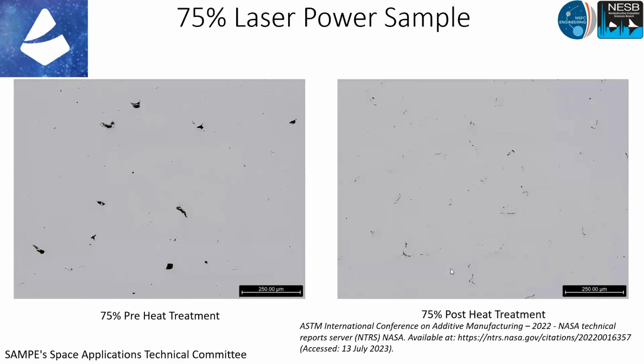But what they do is they actually close up a little bit, making it harder for our CT systems to see them. And that's kind of why we didn't end up seeing them in the CT systems to begin with. So it's an interesting conundrum, when to do the CT. You're probably going to want to do it, at least for computed tomography, before you do your heat treatment, because it will close up the pores and create some interesting issues.